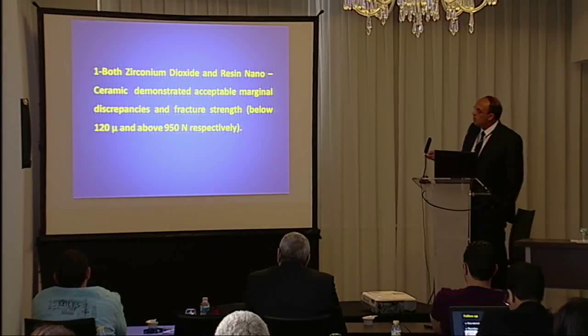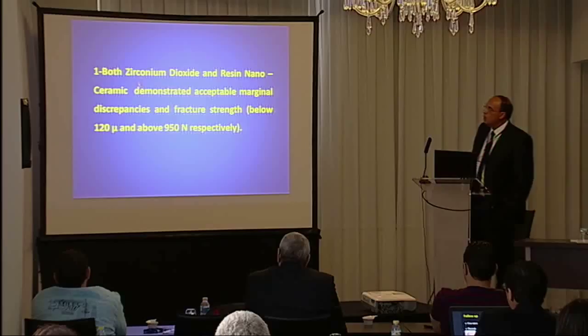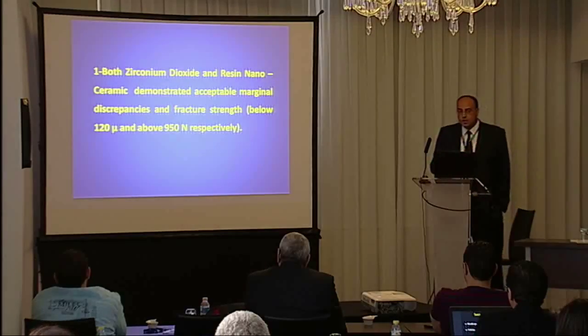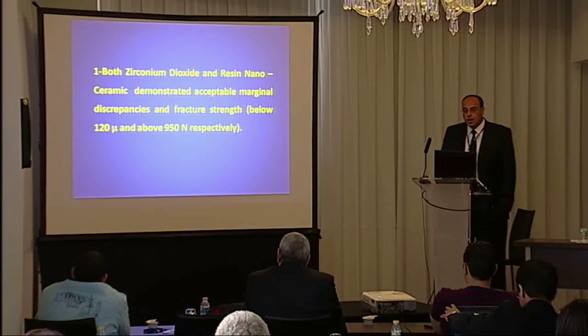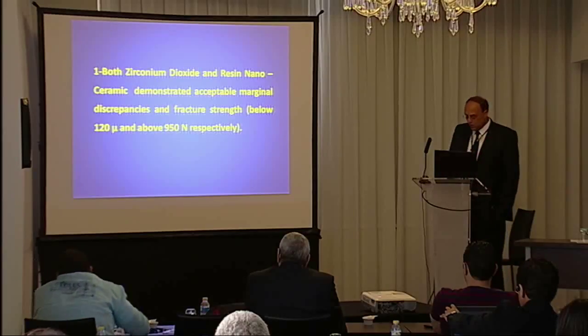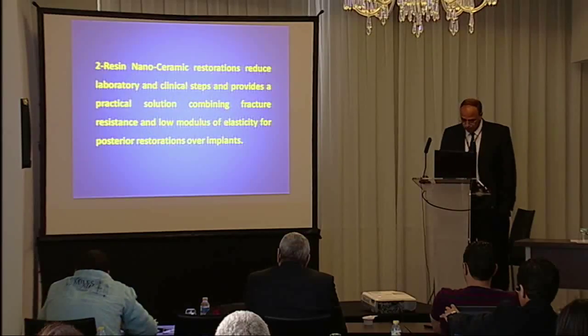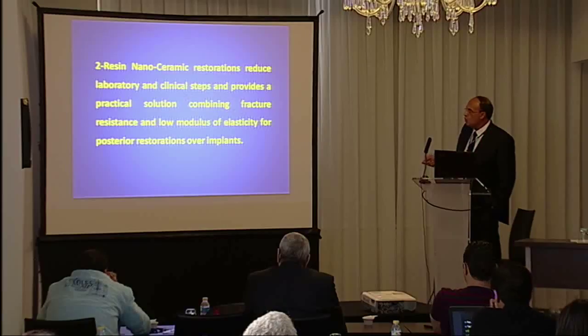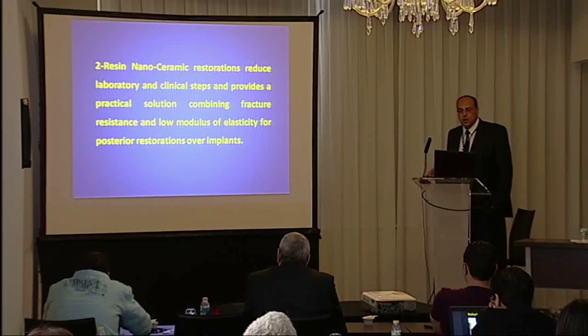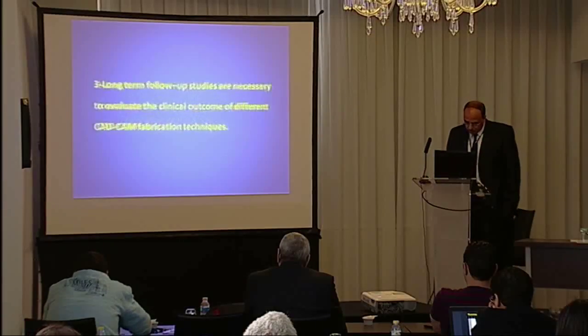Both zirconia and nano-ceramics demonstrated acceptable marginal discrepancy, less than 120 micron, and above 950 Newton. Resin nano-ceramic reduced laboratory and clinical steps and provides a practical solution combining the fracture strength and low modulus for posterior restoration, especially over implants.